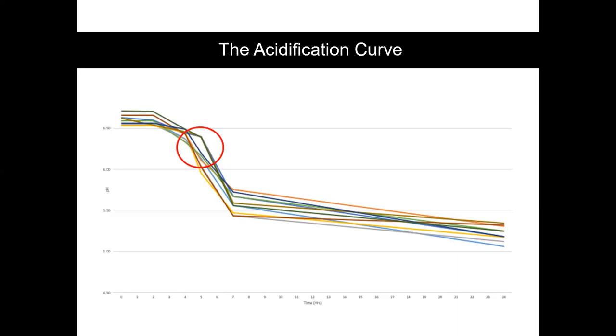But there was one point partway through the cheese make in which a little gap opened up in the pH curves that we plotted. And this gap showed a significant correlation with whether it made a good cheese or not. The gap is centered right about pH 6.3 or thereabouts. Everything that came in above that gap made a truly excellent cheese, and everything that came in below it was awful. It was weak-bodied, over-acid, crumbly, brittle, and it didn't ripen properly. And this marks one of the key process controls for this cheese type.